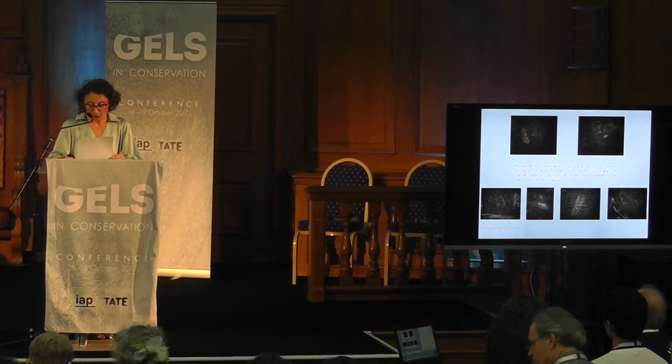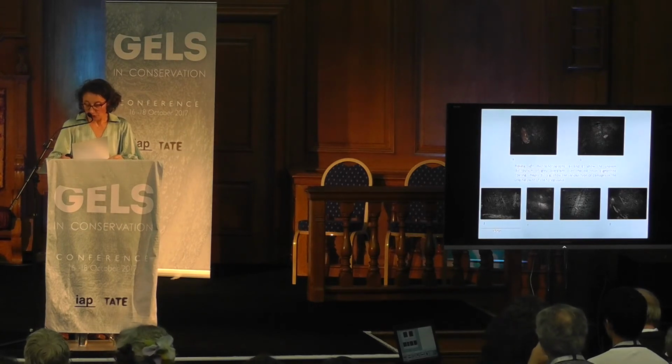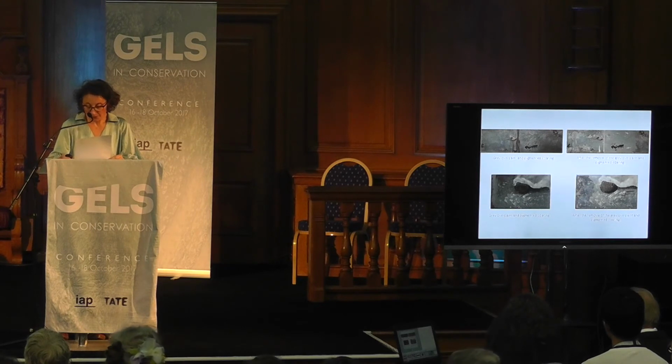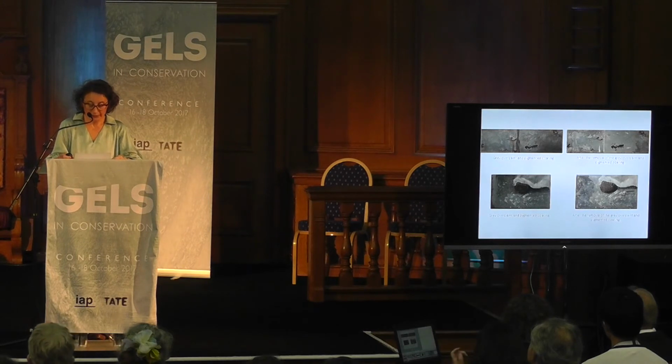In the foreground, the original paint layer is soft and fragile in some areas and more stable in others, while texture also changed from smooth to rich. Brushstroke has been eroded by the use of strong solvent as well as abrasive material. The xanthan gum gel with the 15% benzyl alcohol is applied to the restoration coatings in the same manner described above. Mechanical cleaning, however, is employed more frequently than in the pedestal because of the sensitivity of the original paint layer.